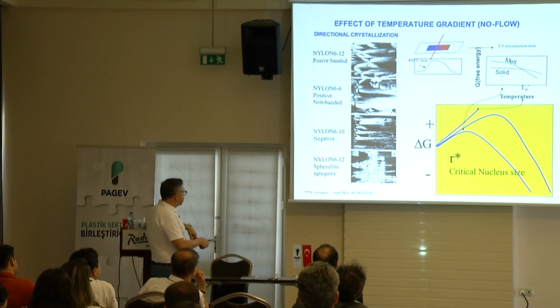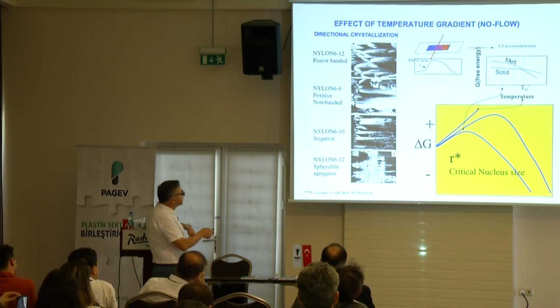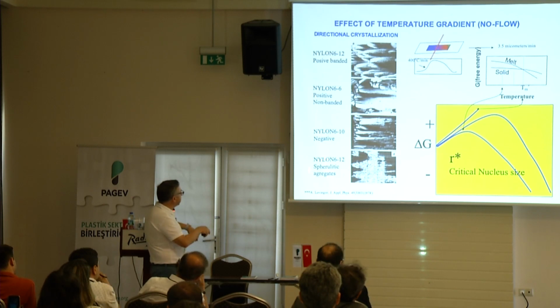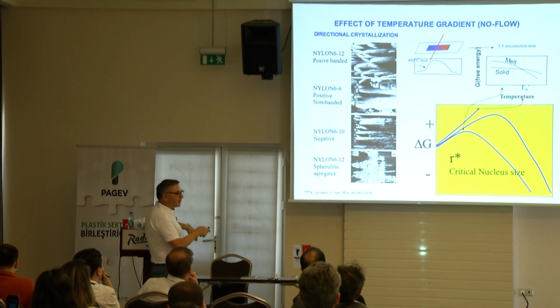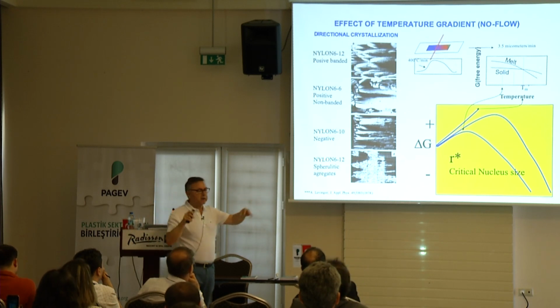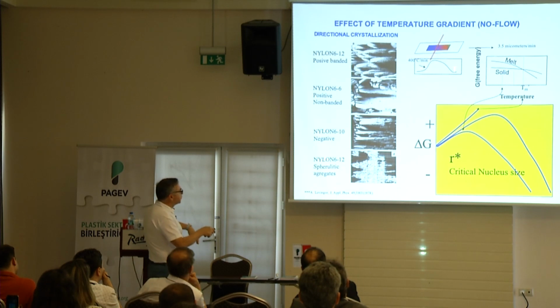There is a very nice guy named Andy Lovinger, a long time ago, 1978. He did this very simple experiment. He made a very thin film of various materials, nylons, onto a glass slide and put basically a hot wire, just very simple hot wire. So you basically have this temperature gradient. And he just pulled it at a very small speed, 3.5 micrometers per minute. So you have a hot region underneath the wire, cold before, cold after, and he created these kinds of structures.